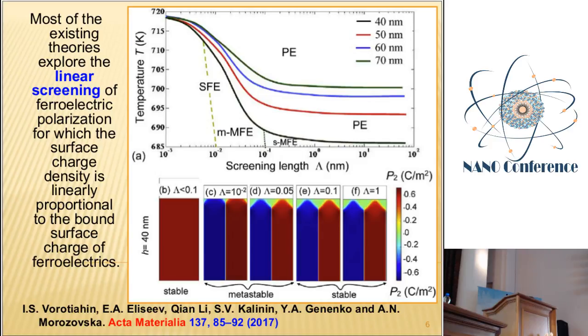Well, experimental results are abundant today, but no comprehensive theory, and especially no analytical theory, has been developed yet. Partly because the cases are material sensitive, environment sensitive, substrate sensitive, electrode sensitive, and so on and so on. But nevertheless, we should do something about this, because even if we consider the linear model of the screening, these models are already known in the literature, you may see from this slide that when you increase the screening length of the surroundings, the conditions for polarization conservation vanish, and as a result you have an additional domain structure, so-called closure domains, at the top surface of the film which is electrically open.